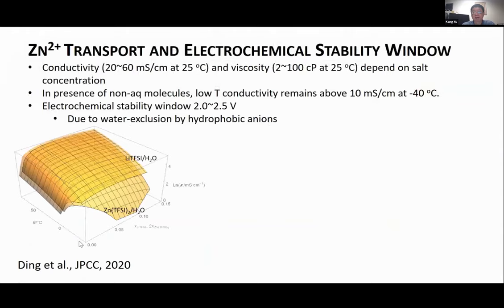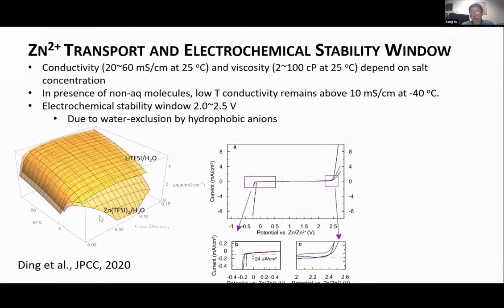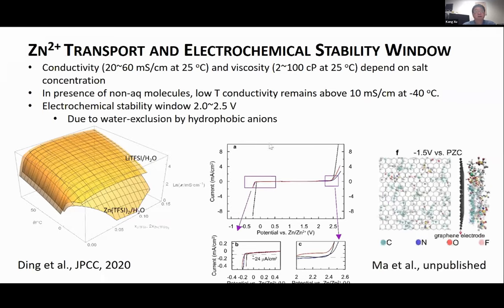And by studying conductivity, we found that zinc TFSI, although it's a divalent cation, is almost as conductive as lithium in the water system. And what's more important is that it has very high conductivity at low temperature, as I show here. At this low temperature end of this 3D conductivity map, you can see that at those temperatures, the lithium salt already precipitated out, salted out, and can no longer serve as a liquid electrolyte, but zinc can. That gives us the opportunity of using this as a low temperature electrolyte.